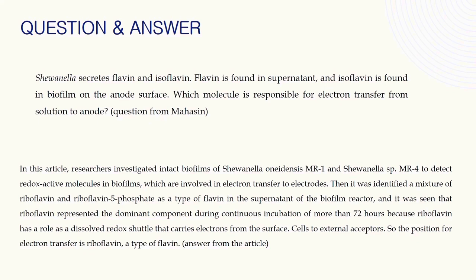The answer from the article is: researchers investigated intact biofilms of Shewanella oneidensis MR1 and Shewanella sp. MR4 to detect redox active molecules in biofilms, which are involved in electron transfer to electrodes. Then a mixture of riboflavin and riboflavin-5-phosphate was identified as the type of flavin in the supernatant of the biofilm reactor. And it was seen that riboflavin represented the dominant component during continuous incubation of more than 72 hours, because riboflavin has a role as a dissolved redox shuttle that carries electrons from the surface cells to external acceptors. So the molecule responsible for electron transfer is riboflavin, a type of flavin.